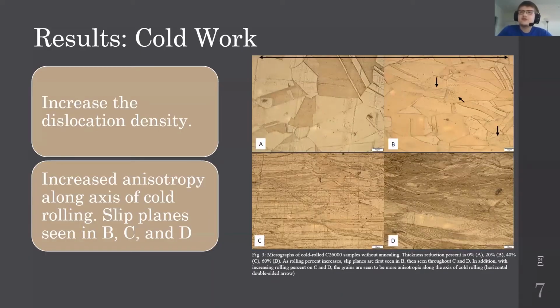So here are some results for the percent cold work. This is a micrograph of the 0-minute annealing time at 0, 20, 40, and 60% cold work. From these micrographs, we found that increasing the percent cold work increases the dislocation density. You can see that it also increased the anisotropy along the axis of cold rolling. And we can also see some slip planes in the 20, 40, and 60% cold works.